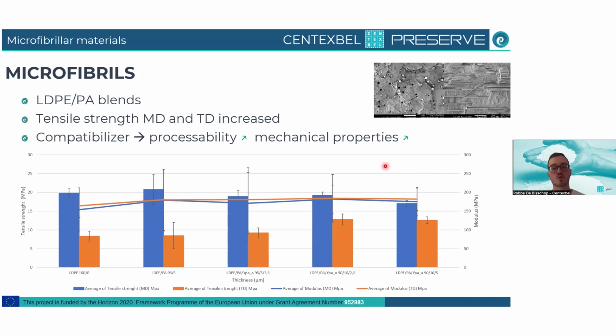We can also see this in the mechanical properties. So if you look at, do we get an improved strength in this material? On the left-hand side, you can see a reference LDPE without any fibrils. And then you can see with polyamide, we do get some improvement. Notably, a very big improvement is with adding a compatibilizer, so really making sure that the matrix and the fibrils are bonded together, so you get this strength increase. And you can see when you look at the orange bar that you almost double this by using these compatibilizers. Also, a compatibilizer will very much increase the processability of your process.